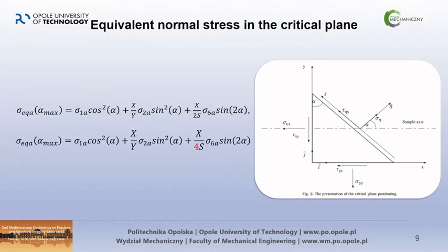And in other articles it has been already presented with the equation here at the top of this one. However, this equation has been presented for metal material, which is an isotropic one, of course, and the composite materials are anisotropic. This is why sometimes we can't straightly use them.